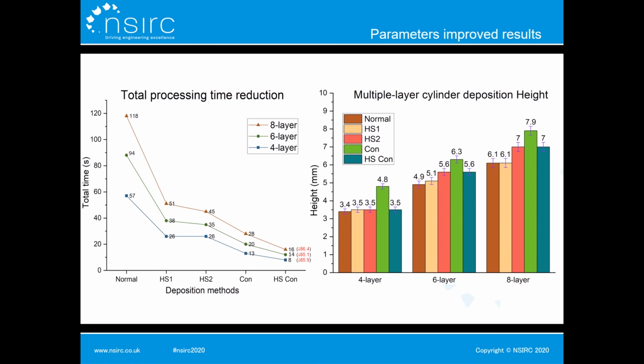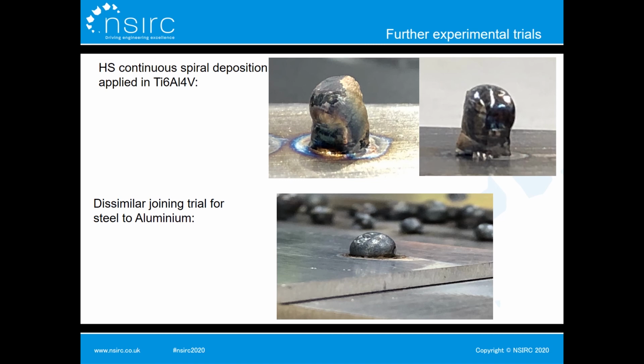The right chart is the height results of these cylinders, but there is not much difference. But because of longer deposition time and lower energy input, the normal continuous spiral has the largest value among them. These are further experiment trials of titanium alloy spiral deposition and dissimilar joining between aluminum and steel. They still need more evaluation and systematic investigation.